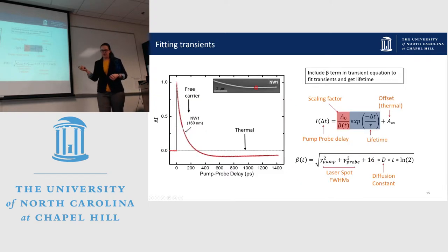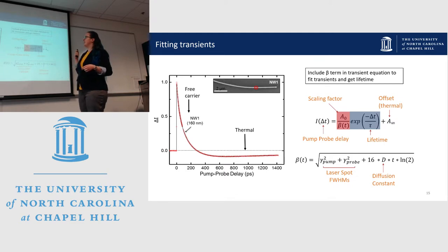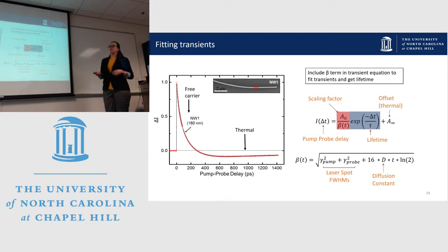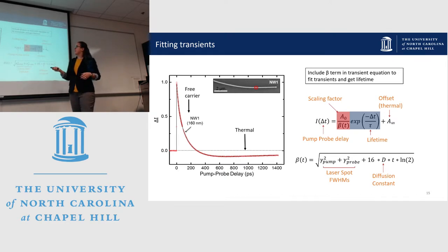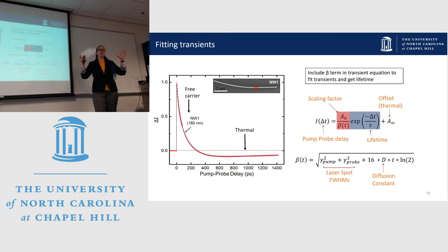Once we have the diffusion coefficient, then we can actually go through and fit these transients and get a lifetime for the recombination. So we use this expression, which looks a little bit daunting, but effectively, it's really just three terms. We've got a term here, which is our lifetime, or how quickly the carriers recombine. We have a term here, which describes the diffusion of carriers. And then we have this offset, which describes this negative going signal, which I haven't mentioned. It's because we're heating up the wire. It's a thermal signal. It lasts long enough relative to the recombination that we can treat it as a constant offset, and it doesn't really change the lifetimes that we calculate.